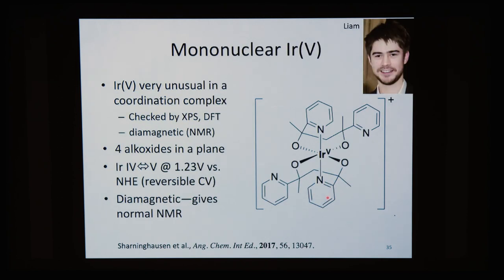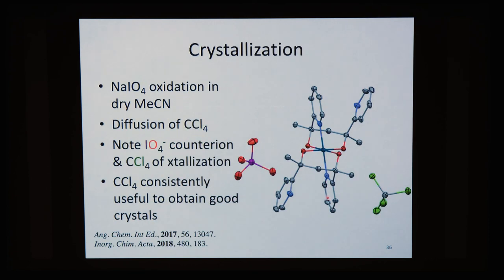And Liam made a ligand here which is capable of putting four alkoxides into the same plane. And in this case, the 5 state is the stable state, and it's diamagnetic and gives a normal NMR. So this is very, very unusual for a coordination compound. So there are all the high oxidation states. And here's the crystallization of Liam's compound.